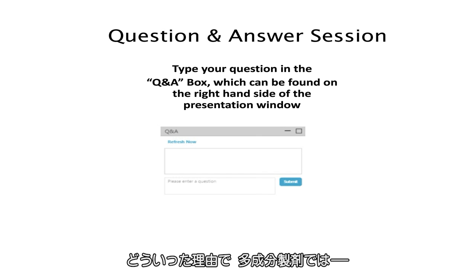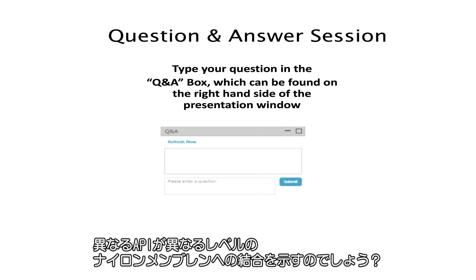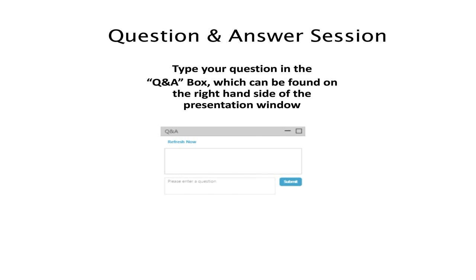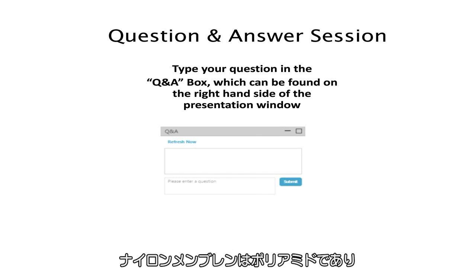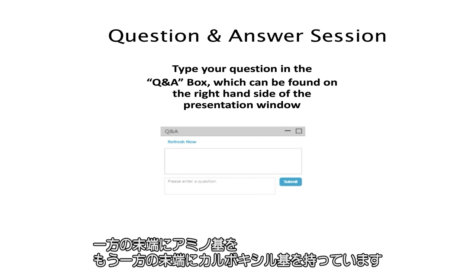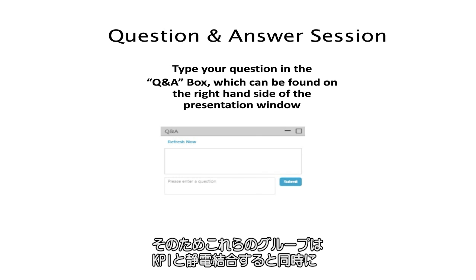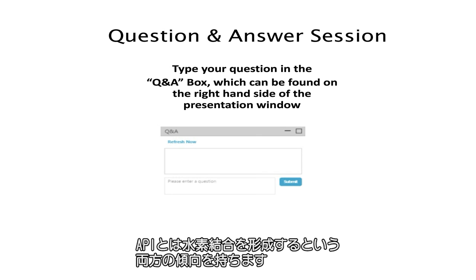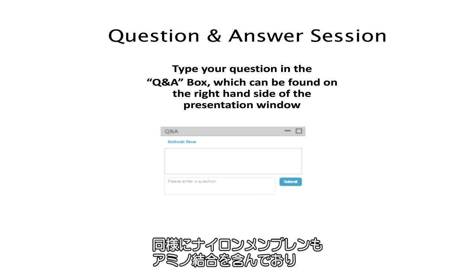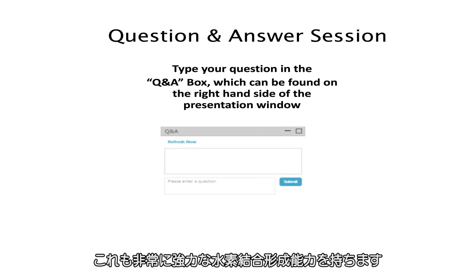Thank you. In a multi-component formulation, why do different APIs show different levels of binding to the nylon membrane? So nylon membrane is a polyamide, meaning that it has an amino group on one end and a carboxylic acid on the other end. So both those groups have a tendency to form either electrostatic bonding with APIs as well as forming hydrogen bonds with the API. Similarly, the nylon membrane also contains the amide linkages, which are also very strong hydrogen bond formers.